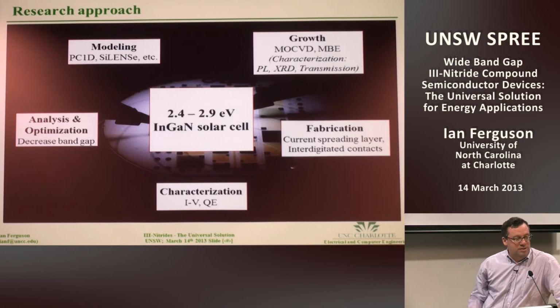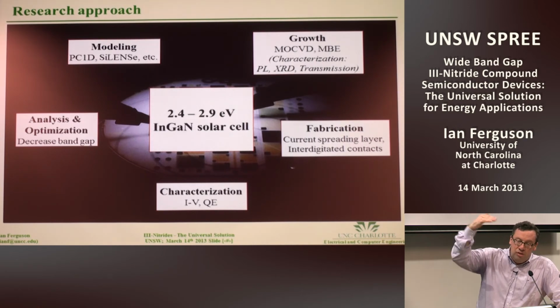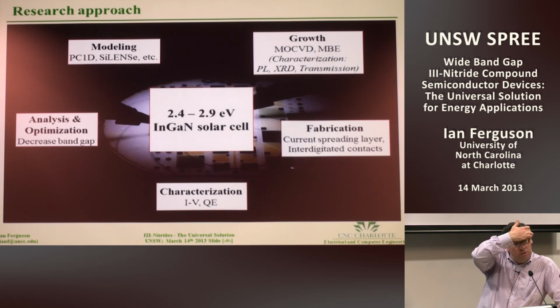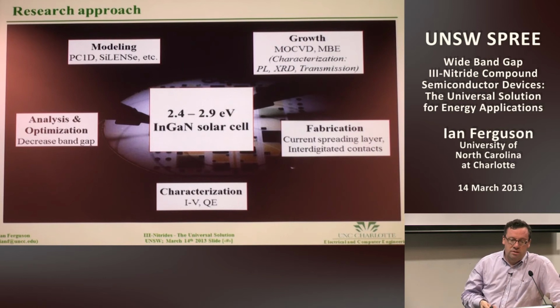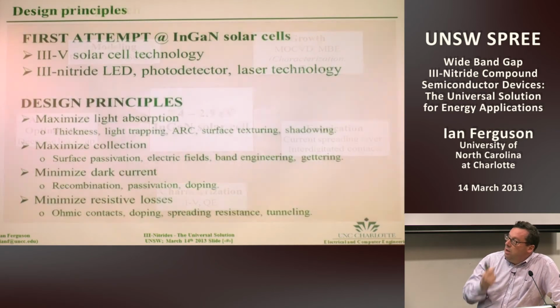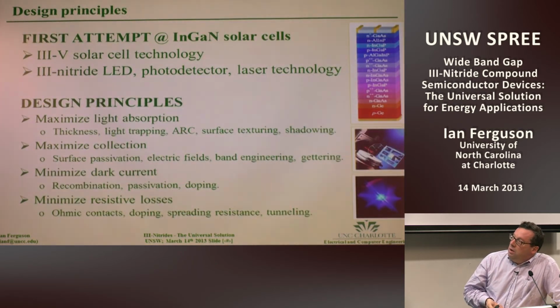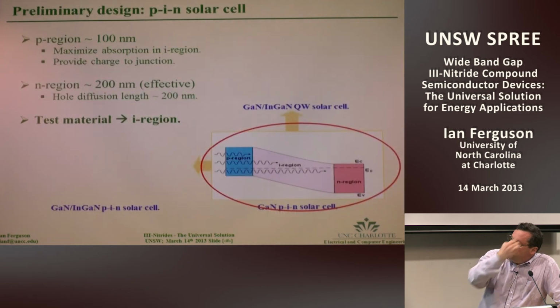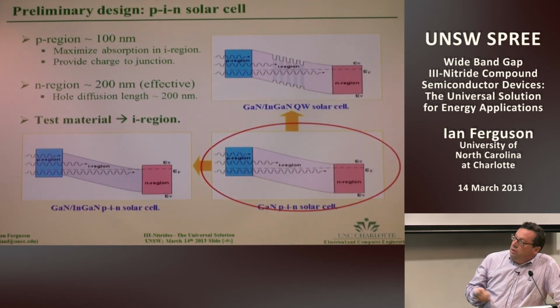So the design of the cell can actually end up being fairly complicated because of these redistributions of charge, associated with the fact that you have a semiconductor that's essentially non-central symmetric. So things we did were to start looking at what type of devices, and we came down to simple PIN solar cells.